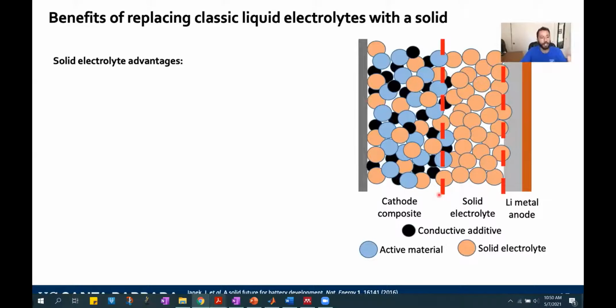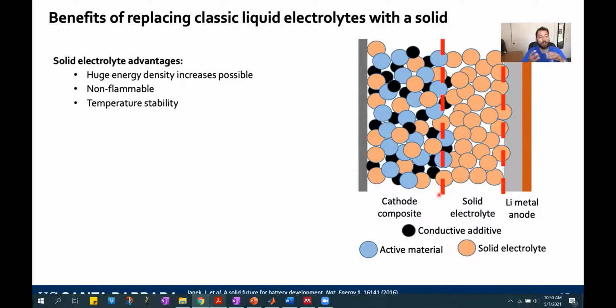So on the solid electrolyte advantages side, we've got a huge energy density increase that becomes possible by allowing us to go to higher voltages and implement a lithium metal anode into our construction. And these things are really what we're shooting for. We want high energy density if we want to displace the fossil fuels out of this. Next is the non-flammable. So the solid electrolyte that we're dealing with here is non-flammable and will not catch fire. It's also stable, so it's not going to become volatile at higher temperatures, and therefore our battery doesn't have to worry about being at those higher temperatures.